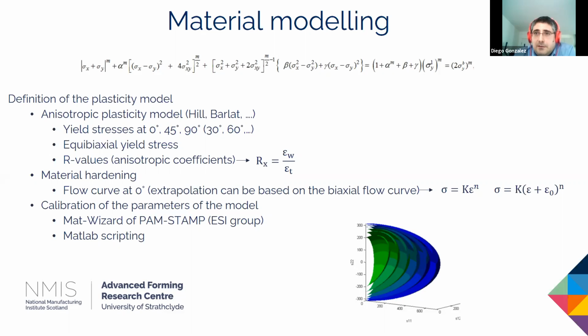And in order to define correctly which type of plasticity model we need to apply for this specific material, we need to consider all the information coming from the lab. So we will consider the yield stresses at different directions within the blank. We will consider the equibiaxial yield stress, and this is a very important aspect because we want to understand how the material behaves in an equibiaxial mode. When we form a component, we will mainly have plane strain and biaxial deformation modes more than pure tensile modes, and we will also use the R values, the anisotropic coefficients, and these will allow us to understand what type of anisotropic model we should be applying.